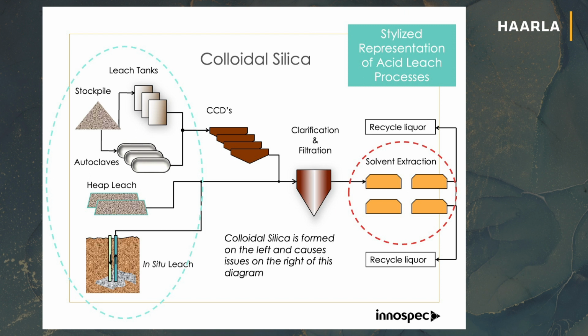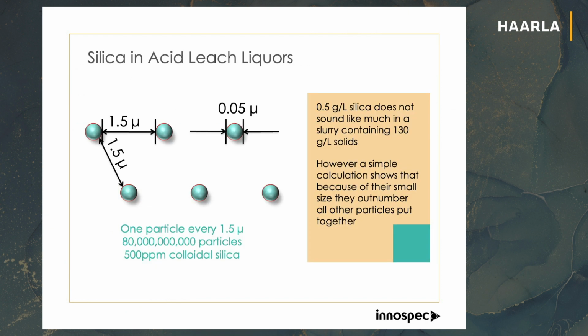So why is the colloidal silica so difficult? First thing, it won't filter. It's too small. It goes through the filter. The second important thing is that even though it's only there at a very small percentage, it's in a very large quantity. If you think of a bag of frozen peas, all stacked together, you've got these small colloidal particles stacked together. That means the silica particles can't separate, they can't settle to the bottom, they're sort of suspended. That's really important to try and control, because if you can't get that settling out, it then has to be removed by filtration, so it impacts the efficacy of your process.